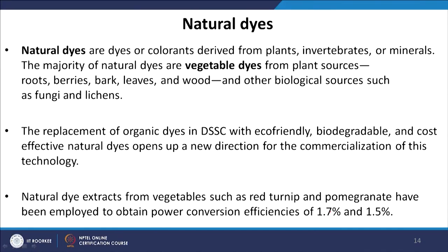The efficiency obtained from natural dyes is not as high as synthetic dyes, and there are reasons for that. Most of the time, natural products come with multiple isomers and other compounds alongside the useful material. In plant or natural chemistry, it is very difficult to extract one particular useful isomer. Because the material is not very pure, the efficiency suffers. However, if a particular component can be extracted selectively, these numbers can be improved.